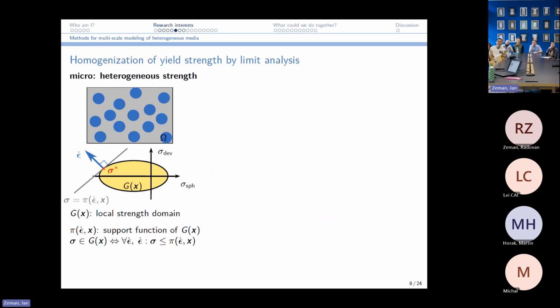So 1 billion elements. If you have to store a single scalar quantity in each element, it means you have to store 1 billion scalars, and that is 8 gigabytes in RAM. Okay. So now if you want to store a strain, with small strain you have 6 times 8 gigabytes. Okay, that gives you an idea. The good thing is we do not have to store the stiffness matrix. There's no stiffness; it's computed on the fly. And for the simulation of fluid flow through 1 billion elements, that took about a couple of hours on a good desktop computer, not a supercomputer. And this is the selling point of these methods, that you can do that.